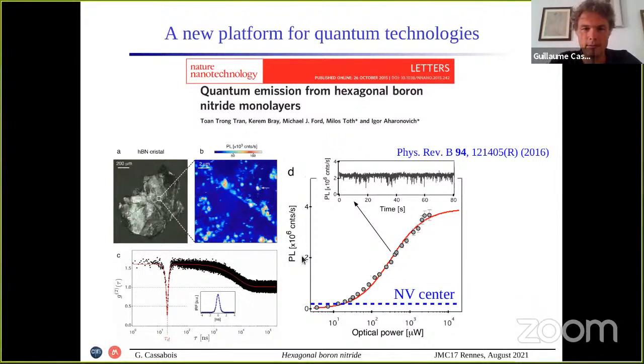Here you have the saturation as a function of the optical power. We reach emission counts of about millions of counts per second, which is huge. For those of you not familiar with this field, here I have plotted the emission level of a typical NV center, which is 10 times lower.